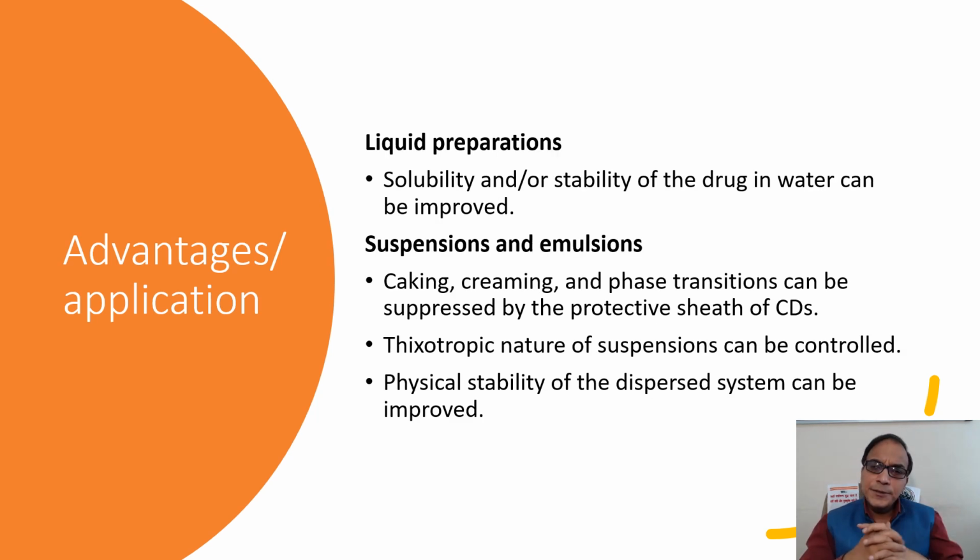For liquid preparations, solubility and stability of the drug in water can be improved with the help of cyclodextrin complexes. In case of suspensions and emulsions, caking, creaming and phase transition can be suppressed by the protective sheet of the cyclodextrins. The thixotropic nature of suspension can be controlled with the help of cyclodextrin complexes, and physical stability of the dispersed system can be improved with cyclodextrin complexation.